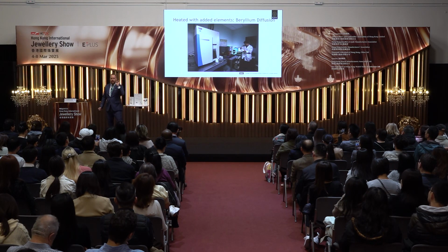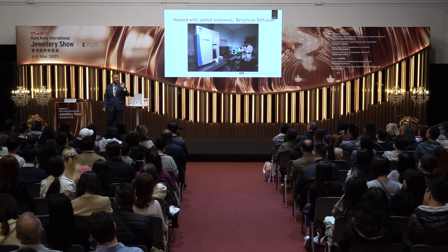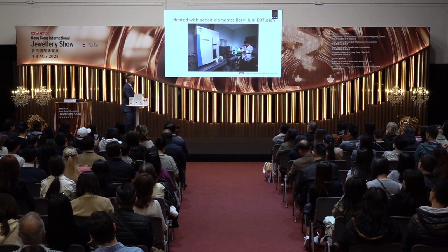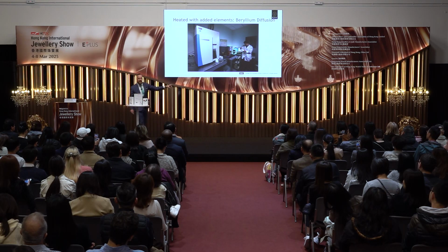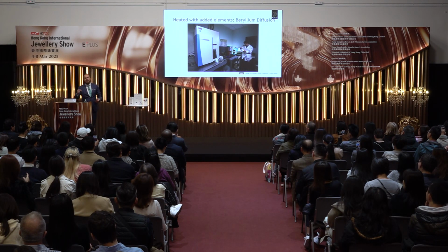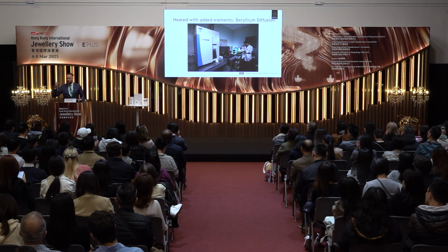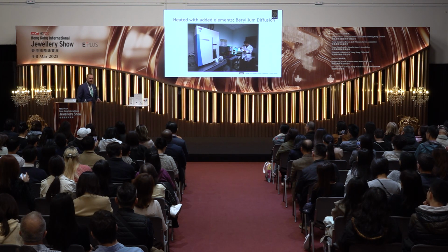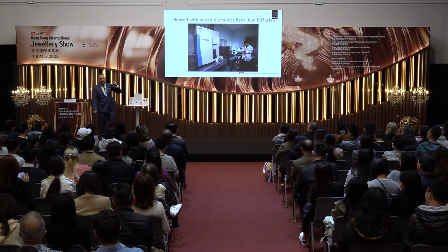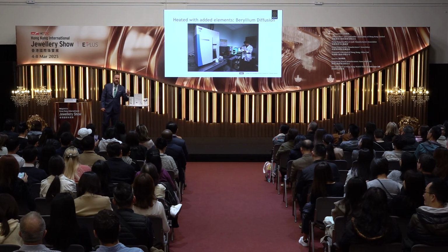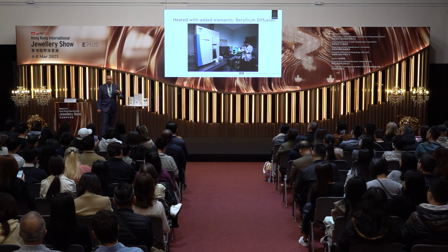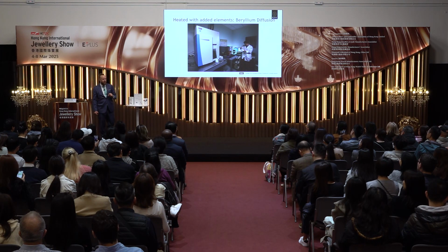But it is a very fancy, very high-tech piece of equipment where we basically analyze your ruby or your sapphire by burning a super tiny hole on the girdle of your stone. The material we burn out gets pulled through this entire big machine, and we are able to detect chemical elements down to the size of 1 part per million. Now that is the equivalent of finding a stamp on a football field. That is the equivalent of going to New York City, and I give you a list of 10 people, and you've got to find those 10 people in New York City.